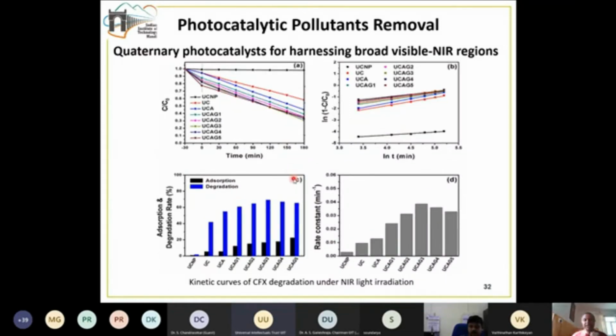For the NIR light experiment, we used the solar simulator, and we blocked the UV light and the visible light, because we can also do this experiment using direct sunlight, but we need to block the UV and visible light to ensure that whatever is happening is because of the NIR light. So we blocked this UV and visible light using a thick band pass filter and allowed only the NIR light to penetrate into the sample. And we found that the UCAG3 sample here exhibits the best photocatalytic activity.